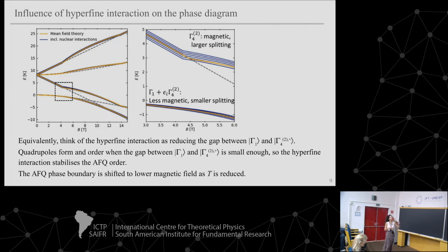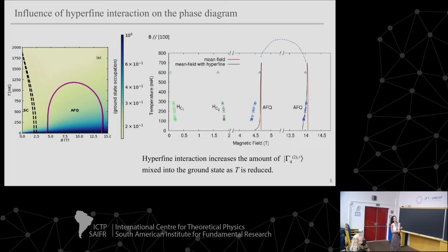Another way of thinking of this effect of the hyperfine interaction is that this is just now a zoom of this area on the crystal field level scheme. It reduces the gap between the two levels, right? So we're mixing these two levels together, and by splitting these, you're effectively reducing the gap between this upper one and this lower one. So that's just another way of thinking about it. The quadrupoles form when the levels are closer together. By splitting the states here, you're actually reducing this gap so that the quadrupole order can form at slightly lower field. So that's kind of what we're seeing, that this just shifts to lower field here.